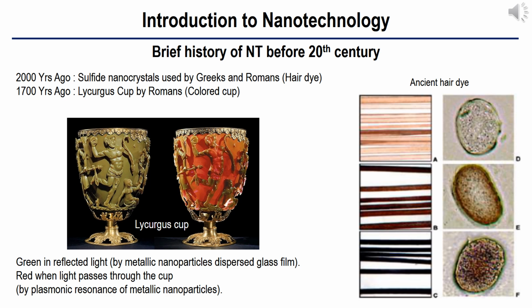It was found that the dichroism, which means two colors, is observed due to the presence of nanoparticles, 66.2% silver, 31.2% gold, and 2.6% copper, up to 100 nanometers in size, dispersed in a glass matrix. The red color observed is a result of absorption of light at 520 nanometer wavelength by the gold particles. The purple color results from absorption by the larger particles, while the green color is attributed to the light scattering by colloidal dispersions of silver particles with size larger than 40 nanometers. The Lycurgus cup is recognized as one of the oldest synthetic nanocomposites.